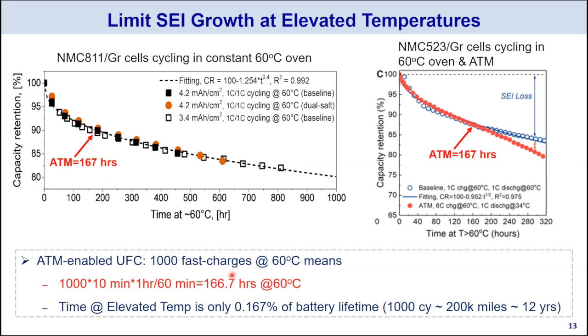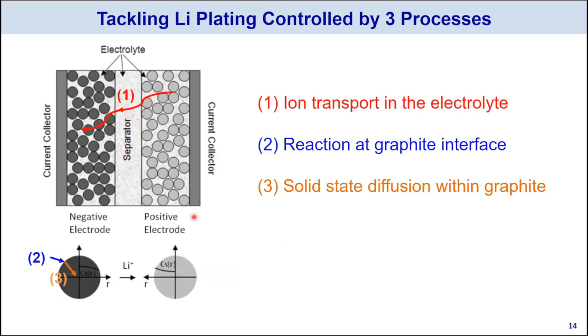Now, this is 1,000 all fast charging, all staying at 60 degrees Celsius. If we follow the USABC criterion, which only requires 25% fast charging cycles, the total time is reduced by a factor of four, and we'll be talking about something like 40 hours. So capacity retention is not an issue. Now, what about our ability to eliminate lithium plating?